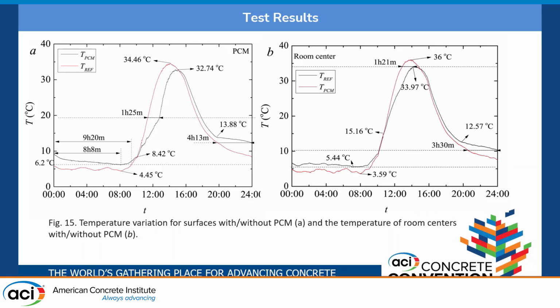So, the room temperature shows a quite similar result. But during the daytime, during the peak temperature hours, the PCM specimen shows significantly lower surface and room temperature than the reference specimen. So what it shows us is that during the nighttime, the PCM releases heat because the ambient temperature is lower than the PCM melting and solidification temperature. The PCM releases all the heat it absorbed to the surrounding environment, and it increases the room center temperature. But during the daytime, when it goes over the PCM melting temperature, it absorbs all the heat and prevents the temperature increase.